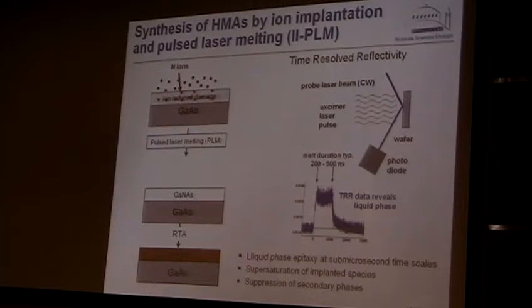Yeah, as I said, we try to have uniform nitrogen because we implant different doses and different energies. So we can implant some dose deeper and some shallower. But there is a gradient coming from the fact that the closer you are to the surface, the faster it can escape. So close to the surface, there is some gradient of nitrogen. There is less nitrogen, basically. Because nitrogen wants to escape from this. It doesn't fit into it.